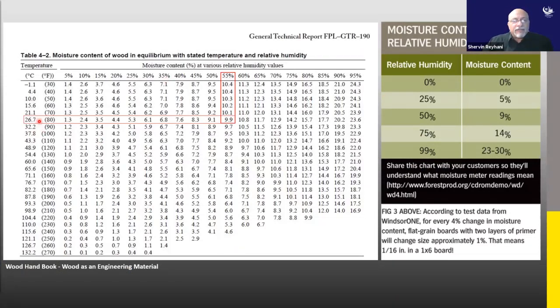I won't go through this exercise. It's just to very quickly show you the effect of moisture compared to what it actually is. So at 55% relative humidity and at 26 degrees Celsius, you're looking at about 9.9% moisture content in the material. So we said roughly 8 to 12% moisture content is acceptable. Now, for mold to grow on lumber, we need to be within this range here: 99% relative humidity and moisture content of 23 to 30%. So to give you an example, even with today's temperature of 31 or 32 degrees and humid, depending on the humidity, it has to be 95% humidity before exposed lumber can actually reach that 24% moisture content. That would obviously promote the growth of mold.